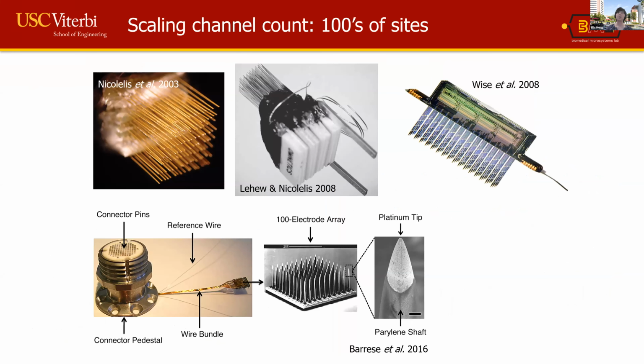All right, so the previous devices I showed are relatively low channel count. And so, at 32 and 64, it's really not at the level that a lot of neuroscientists would like to have. It's possible to scale to hundreds of sites with some of the traditional technologies I mentioned earlier like microwire. But if you look on the back end, the amount of packaging to connect to each one of these is pretty substantial, and that becomes experimentally difficult to implement, especially on small animal. It's quite bulky. These are quite prone to failure. In many cases, people will report that the connector has snapped off, leaving a device in the tissue, but essentially it's rendered, the experiment has to end because you can't connect to any of the electrodes that are remaining in the brain.